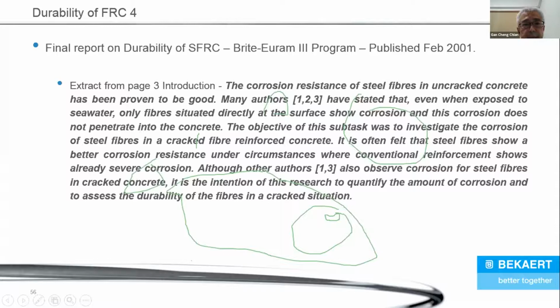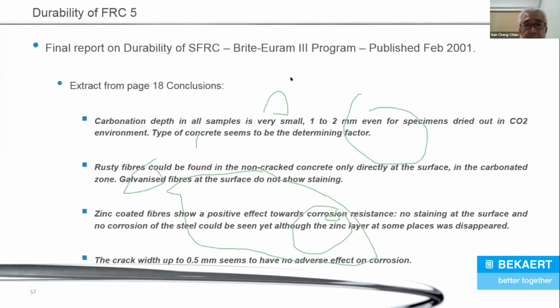And the final conclusion made from this durability study of FRC is this: carbonation depth in all samples is very small, 1 to 2 millimeter, even for specimens dried out in CO2 environment. Type of concrete seems to be the determining factor. Now, your precast segment is normally 200 millimeter to 500 millimeter thick. Now, carbonation is only 1 to 2 millimeter. So this is a non-structural problem.